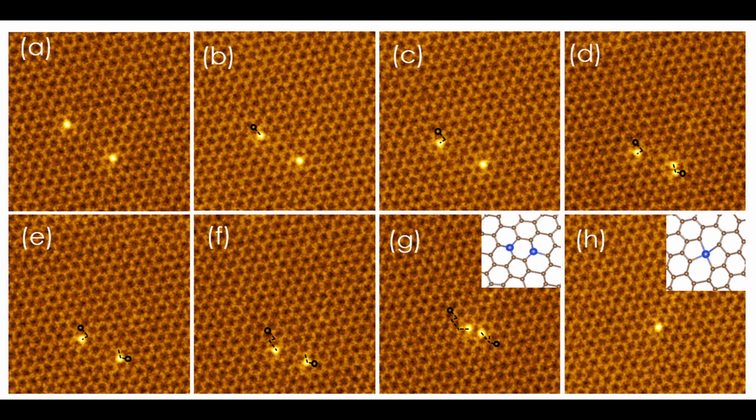together. Here we begin with two three-fold coordinated silicon dopants that have been inserted into the graphene. Using the E-beam, we were able to step them toward each other until they were positioned together in the same hexagonal cell. At this point, one of the silicon atoms was unintentionally ejected from the lattice and lost, leaving a single four-fold coordinated silicon atom.